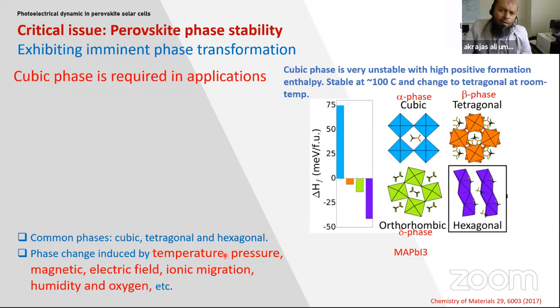And actually, even with these interesting phenomena, perovskite is an archetypal phase transformation system, where this material can easily change phase crystallinity due to a simple change in temperature, pressure, electric field during the operation of the device, humidity and oxygen, and many other triggering factors for this phase transition. The common phases that perovskite can have are a cubic structure and tetragonal, and it can also be in the form of rhombic, hexagonal, and monoclinic.